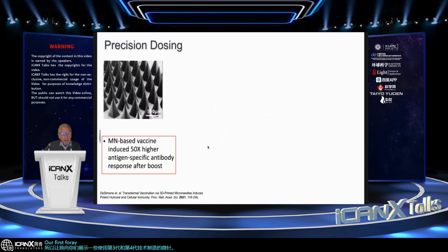Our first foray into this was using our modestly high-resolution printer, 30 micron resolution. We made simple designs. We coated these 3D printed microneedles with vaccines. We delivered them into the dermis. And what we found in this paper we published, we found a 50-fold increase in antigen-specific antibodies simply because we're doing precision delivery of the vaccine to where the locus of the highest population of the migratory immune cells was. So, transformative, but we sort of knew what this result was going to be.